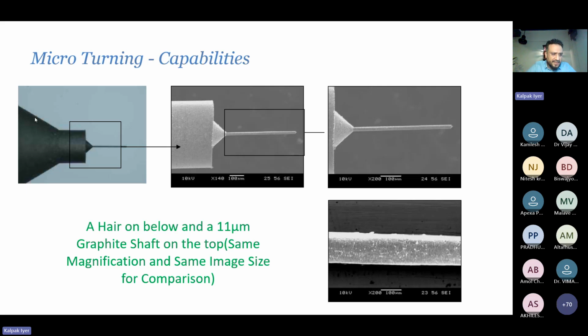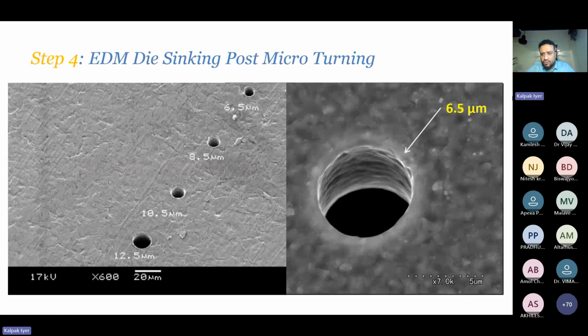As you can see on the leftmost photo, the whole thing is first turned. At the leftmost boundary, you can see micro turning, and then that turned shaft is further chiseled down through further turning with a very small nose radius single point cutting tool and achieved 11 microns. And when this was made, this was the smallest hole made through the EDM process, of 6.5 microns. So that turned electrode was further turned to 5 microns, and then a 6.5 micron hole was made in stainless steel. Quite interesting that it was possible to do this.